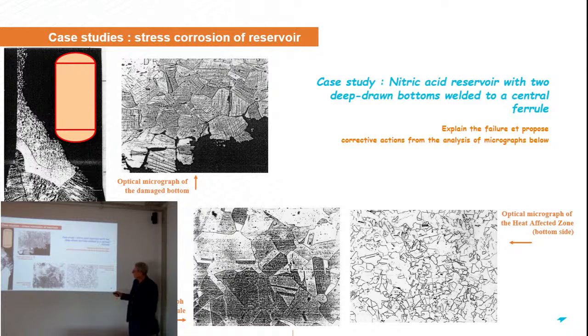So you can see very simply here that the failure is due to some corrosion, and when you make a higher magnification image here of the part that is damaged, you can see that the corrosion is intergranular, which is often the case, and you can see in the metallurgical grain of the material some slip traces. And these slip traces are probably due to some deformation in the material. And this is the part here which is deep drawn. Usually, when you deep draw a part, you do that at low temperature, at room temperature. So usually you have to make a heat treatment afterwards to release the stress.